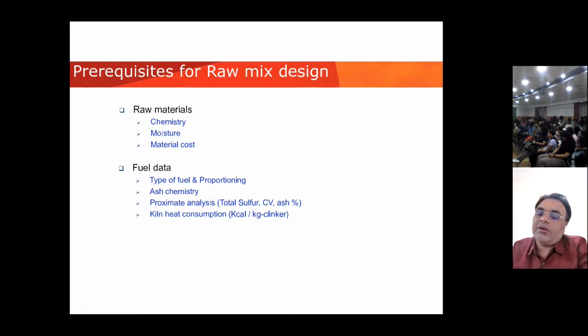At 150 degrees Celsius, the moisture of the raw material, whatever raw mix you have ground, is finally evaporated. After that, entering the different system, the temperature is 300 degrees Celsius. Finally, in a different cyclone, the same material is at 600, where there is dehydration, or calcination of magnesium carbonate. And since limestone is basically calcium carbonate, for making clinker the basic important parameter is your lime, right? So at a temperature of 800 to 850 degrees Celsius, your limestone, calcium carbonate, is dissociated into lime and carbon dioxide. This is the stage where carbon dioxide is released, at 850 degrees Celsius, right?